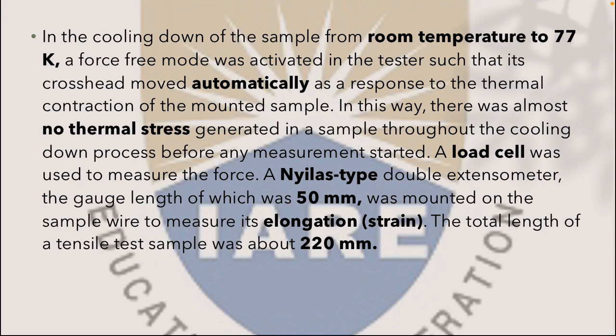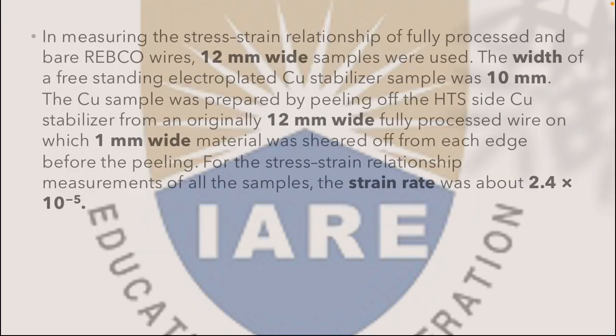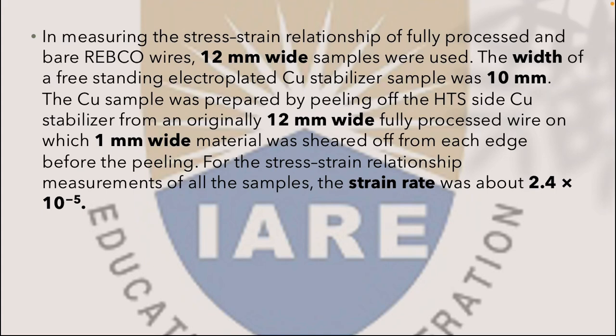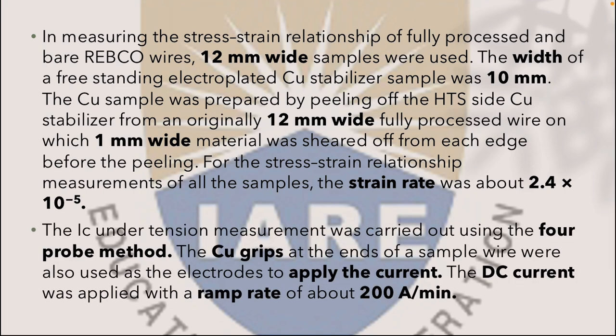The total length of a tensile test sample was about 220 mm. In measuring the stress strain relationship of fully processed and bare REBCO wires, 12 mm wide samples were used. The width of a freestanding electroplated copper stabilizer sample was 10 mm. The copper sample was prepared by peeling off the HTS side copper stabilizer from an original 12 mm wide fully processed wire, on which 1 mm width of material was sheared off from each edge before the peeling. For the stress strain relationship measurement of all the samples, the strain rate was about 2.4 × 10^-5.